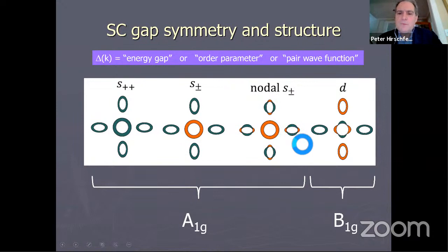And then it's also possible from the symmetry point of view, and you also find sometimes when you do rigorous calculations, that there are nodes of the superconducting gap on certain sheets. So just like the d-wave state, there is a place where the gap goes to zero, and that means there are a lot of quasi-particle excitations possible because the gap is small in those directions. Okay, those are all S-wave states. Why? Because if I rotate each picture by 90 degrees, I get the same state back again. On the other hand, there's also the d-wave or B1g representation that's possible. And that you can see by rotating the picture, you get an overall sign change of the order parameter.